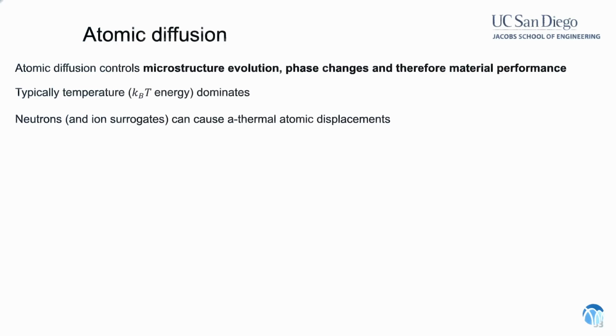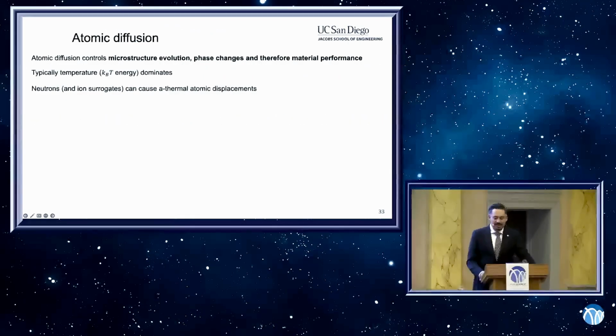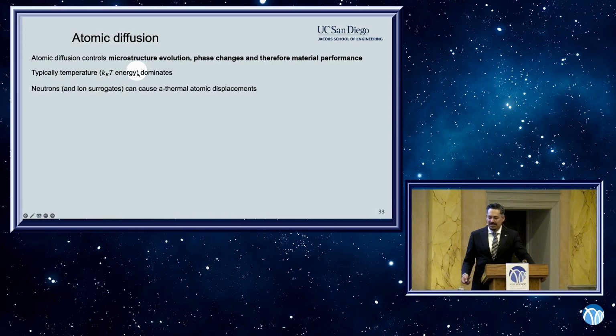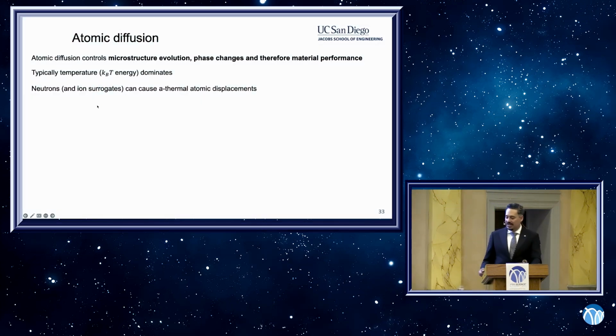So to learn a little bit more and to think about ways that we might be able to address these problems, I want to take a step back and talk about atomic diffusion in general, because atomic diffusion is really what controls phase evolution, phase changes, and therefore the material performance. And typically, when we think about diffusion, we think about the temperature, right? So k_B T energy dominates. Boltzmann constant times temperature is the energy that dominates. But again, for material exposed to a fusion reaction, the fusion neutrons and ion surrogates, a lot of experiments are done with ions as surrogates, you can have athermal atomic displacements.